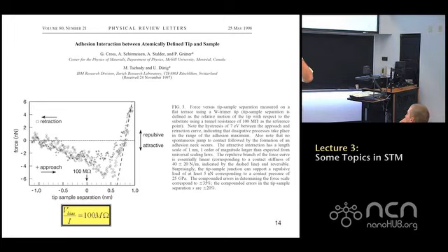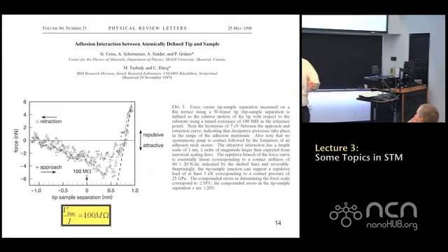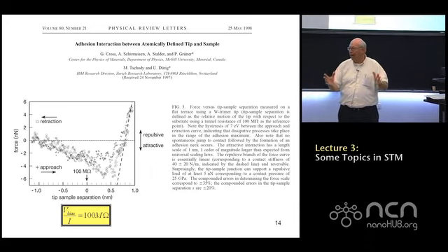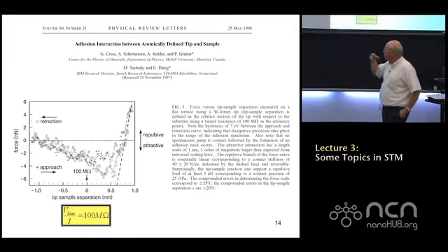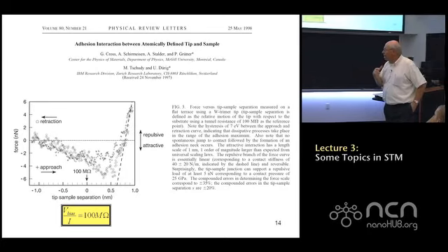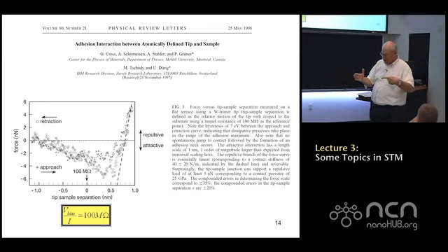And then from the deflection of the cantilever, they can infer absolute force values, what the force of the tip is on the substrate. That's labeled on the left. What they found was that as they moved the tip closer to the substrate, first there was an attractive force that caused the cantilever to bend towards the tip. That's represented in this diagram by negative force values.